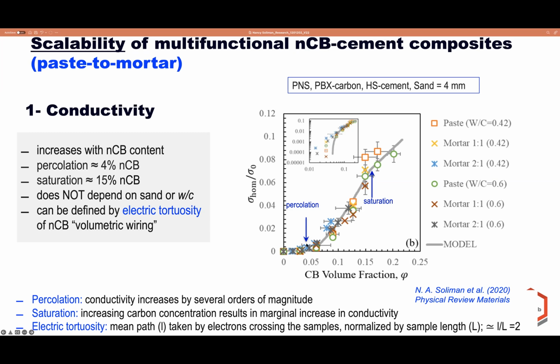This is the percolation threshold, where the conductivity increases by orders of magnitude. And at 15%, we see the saturation point, where there is only a marginal increase in the electrical conductivity. And what we also found here, from analogy with the diffusion problem, is that the electrical conductivity of the composite is driven by electric tortuosity.